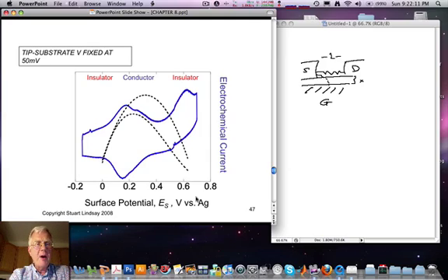So on this plot is shown, first of all, a cyclic voltammogram for a monolayer of these oligoaniline molecules. And you see as the potential is increased, this first oxidation process here, this peak would represent the formal potential. As one continues the oxidation, the current falls as fewer molecules remain to be oxidized.